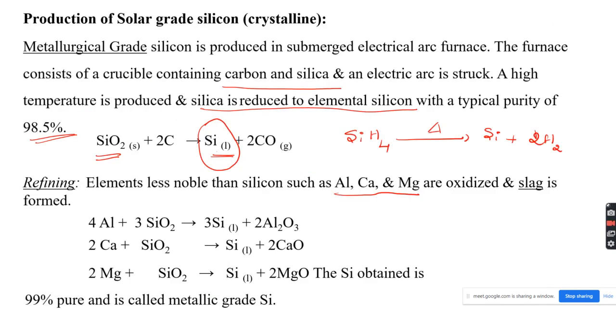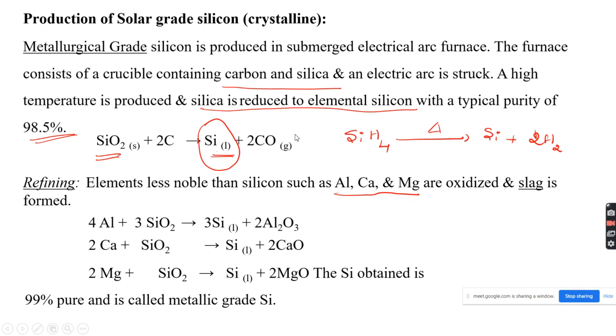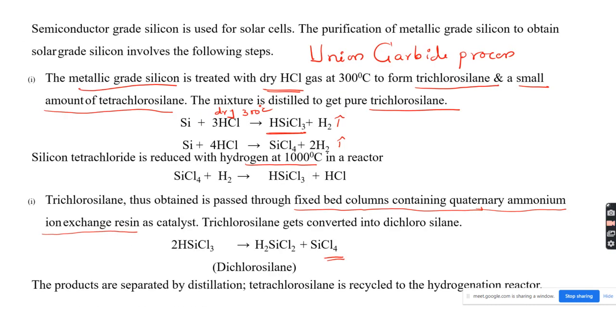First, we observe the three grades of silicon: metallurgical grade silicon, solar grade silicon, and semiconducting grade silicon. Here, the metallurgical grade silicon is produced in a submerged electric furnace. The furnace consists of a crucible containing carbon and silica, and an electric arc is struck. At the high temperature, silica is reduced to elemental silicon. Sometimes impurities less noble than silicon, such as aluminium, calcium and magnesium, get oxidized and slag is formed.